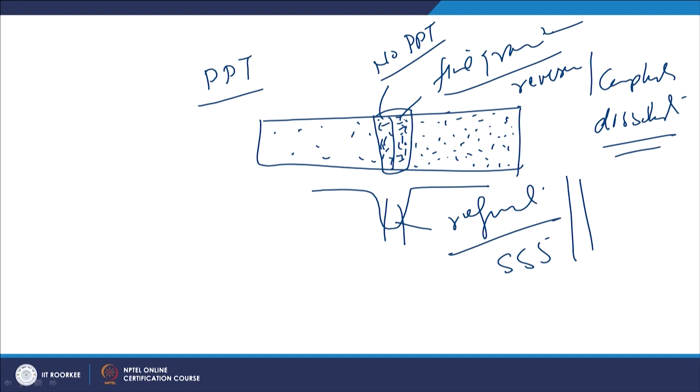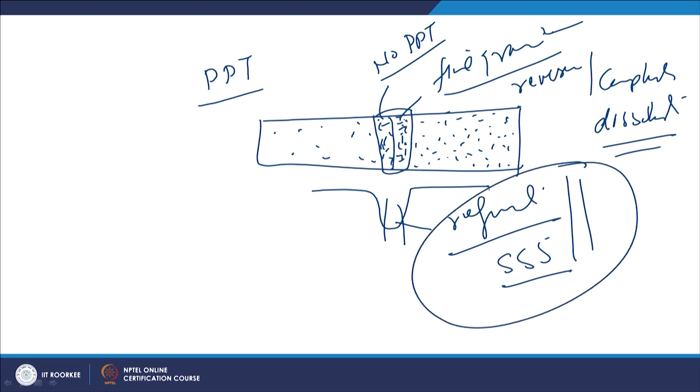So although dissolution will be leading to solid solution strengthening and the fracturing and refinement of the particles will be leading to grain refinement, despite the combination of these two strengthening mechanisms, the major factor contributing to this kind of metal system was the formation of the precipitates, and if these precipitates are lost, then we will be losing the hardness, we will be losing the strength of the joint. So this is the case where solid solution strengthening and the refinement are not working at all. It was the formation of the precipitates that was primarily responsible for the strength of such a metal system.